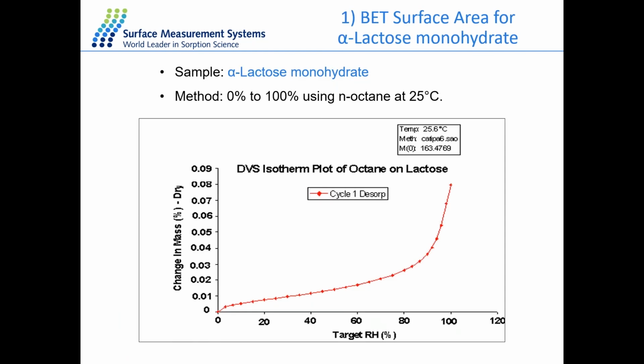So the first example I have here is with alpha lactose monohydrate, where we perform the octane sorption at 25 degrees from 0 to 90 or 100% RH with 5% intervals. But what we use for calculation is basically just between 0.05 and 0.35, only using these points. So we have the octane isotherm for the sample, and it's a quite good type 4 isotherm.